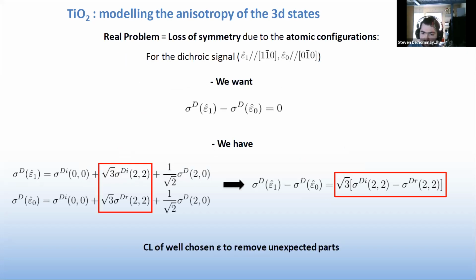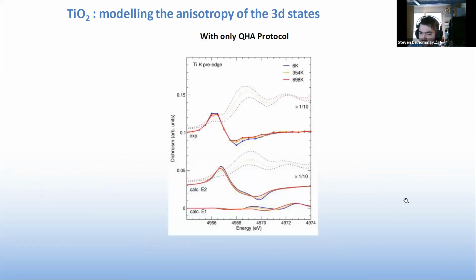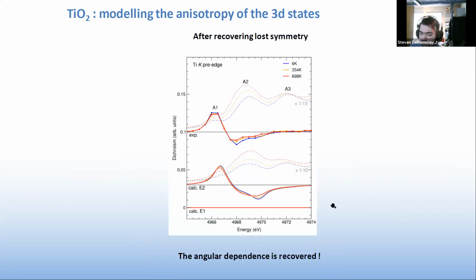I can explain if you want, but the idea is to use a well-chosen linear combination of orientations so that we can get rid of the unwanted term. And in the end, as you can see, when we use this, we can recover the zero contribution to the spectra while keeping the same conclusions we had before. So we managed to at once keep the effects given by the loss of symmetry and correct the problem that they also bring.